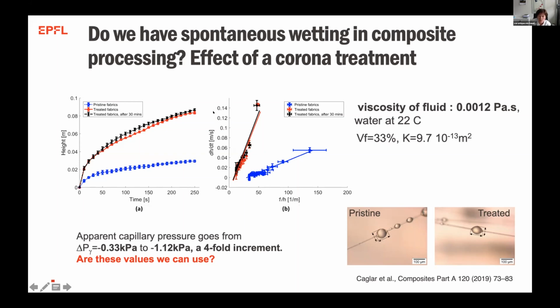And if you analyze all this, you can get the apparent capillary pressure drop. We can see that in the case of the pristine fabric, we had minus 0.33 kilopascal. So it wets, but it's a very small value. And in the one that was treated with corona, we have minus 1.12 kilopascal. So it's a four-fold increment, but it stays, of course, very small.